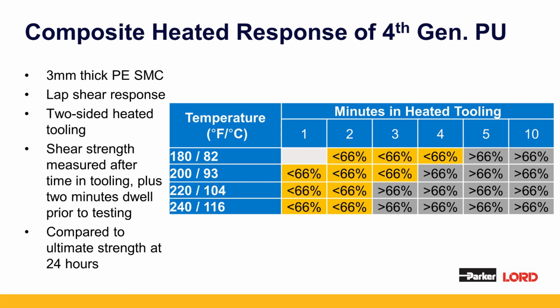In this case, we used lap shear response on 3mm thick polyester SMC and a two-sided heated tooling. The lap shear strength was measured after that particular time in the tooling, as shown by the column on the right-hand side, 1 minute, 2 minutes, 3 minutes, etc., all the way up to 10, and then a 2-minute dwell time prior to testing. This was then compared to the ultimate strength on the SMC after 24 hours of room temperature curing. What we can see here is that at the various temperatures, 82 Celsius up to about 116 Celsius, or 180 Fahrenheit to 240 Fahrenheit, we can rapidly develop greater than 2/3 of the strength of the ultimate yield of the product for this SMC within a short amount of time just by using this heated tooling.